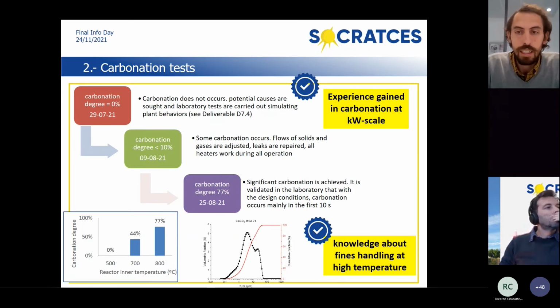Regarding carbonation, it's important to note the significant improvement that we are achieving thanks to the knowledge gained within the operation. Now we are obtaining large reaction extents, up to 77%, when we are operating the carbonation reactor at 800 Celsius degrees. And thus we are demonstrating for the first time at kilowatt scale, with kilograms of materials, that carbonation reactions can occur in several seconds, just in several seconds, which is a main outcome of this project.